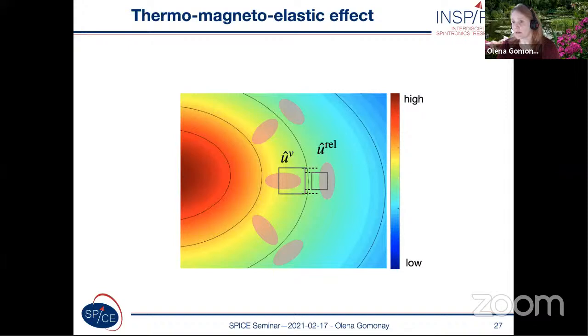And it's natural that the volume expansion is proportional to the temperature. So locally, the volumes in different areas are different. If we look at the interface between cold and hot region, we see that these two squares do not fit each other, so they have different lengths. So we have incompatibility of strains, and this incompatibility should be compensated by some plastic deformations, which are depicted here with the ellipses. And what is nice, these plastic deformations are shear deformations in the sense that they have some preferable axis of elongation.